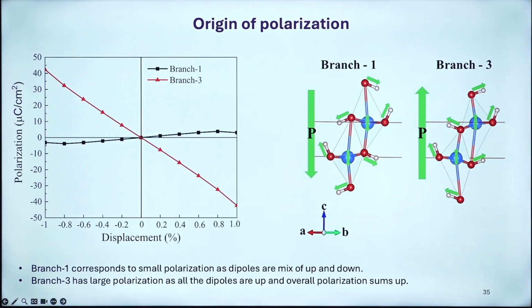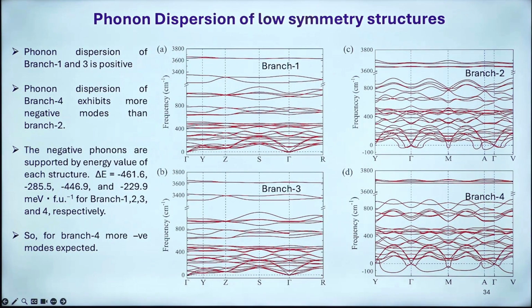Yes. So if you go back, the displacements, are you displacing all the possible atoms, showing that phonon mode? Yes, yes, yes. Otherwise we cannot get the entire phonon dispersion relation. First I will get the space group and the CIF file. Then with that CIF file, I have to once again compute the phonon dispersion for the 2 by 2 by 2 cell in this particular space group. Then I will get the entire dispersion here, and I want to see whether I am able to have a stable structure without any soft mode or imaginary phonon mode in this particular space group.